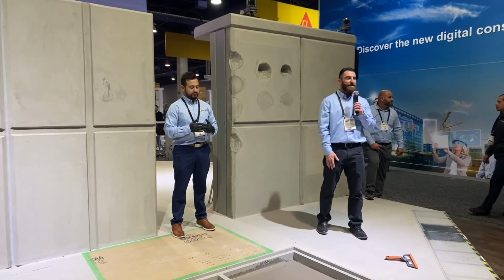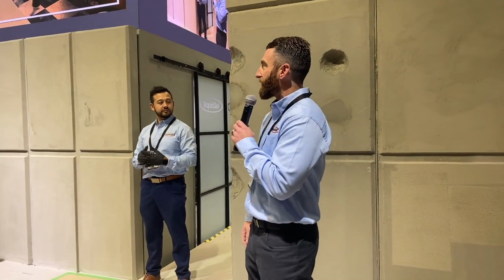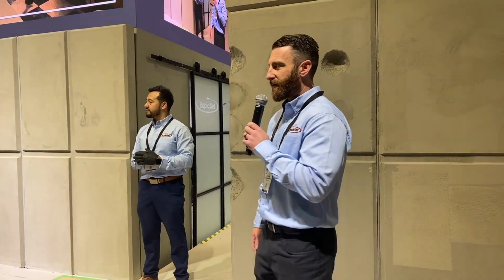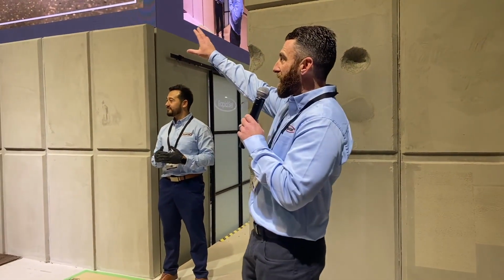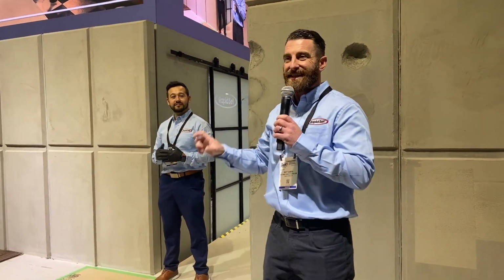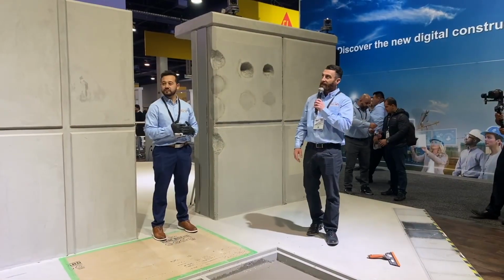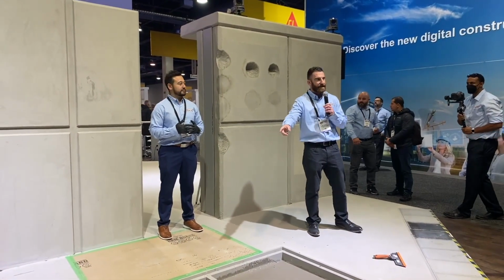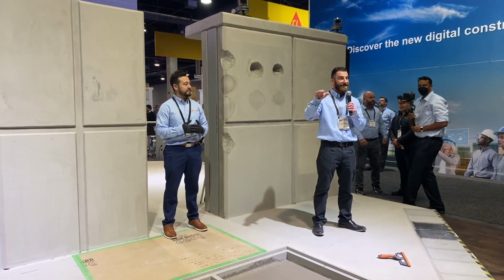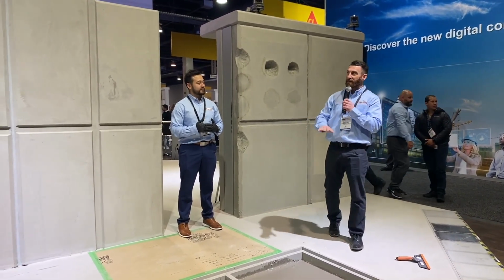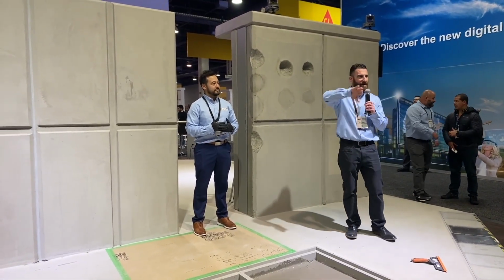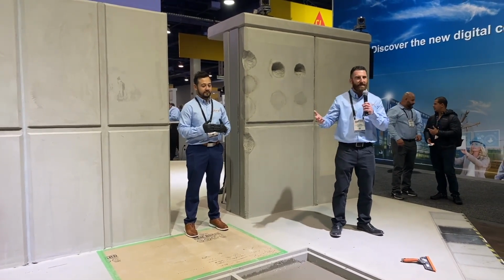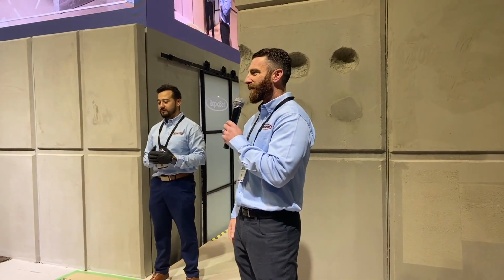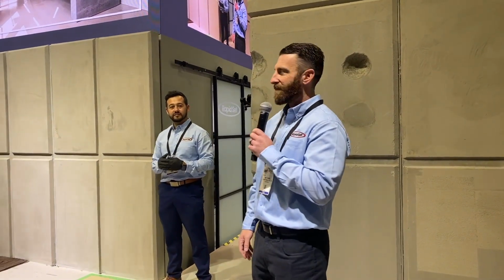The Willis Tower in Chicago, this is when they used multiple products. They used the True PC. They had to get a bunch of different colors on the floor. But the biggest challenge, if you could see on that previous screen, was there was a stage. It was a 6-inch high stage, and they needed to get that below the weight requirement. So what they did is they used our level floor product. They used a lightweight aggregate to build it up to 6 inches thick, and they coated it with True PC. They even used a slip form for that vertical face. So the job came out so well, they were actually awarded 17 more floors on the Willis Tower.